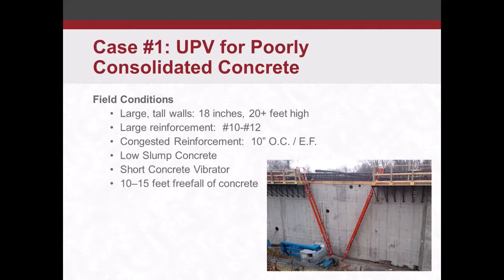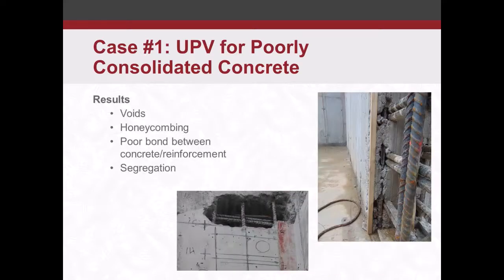The free fall can cause some segregation, which we saw. Some voids, honeycombing, concerns about the poor bond between the concrete and the reinforcement. You can see the picture there on the right. You can see obviously there's some voids here, and there's literally no bond between the concrete and the reinforcement there, very, very little. And segregation, as I mentioned.